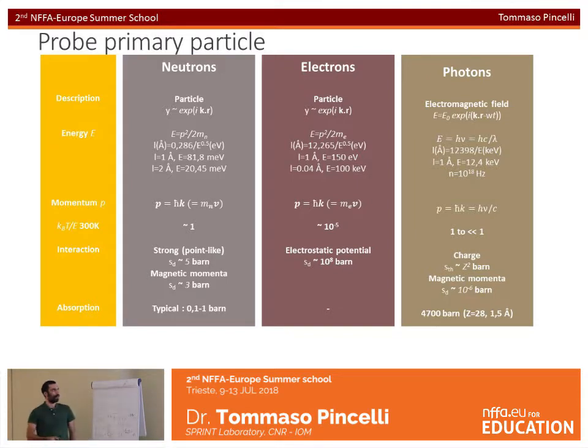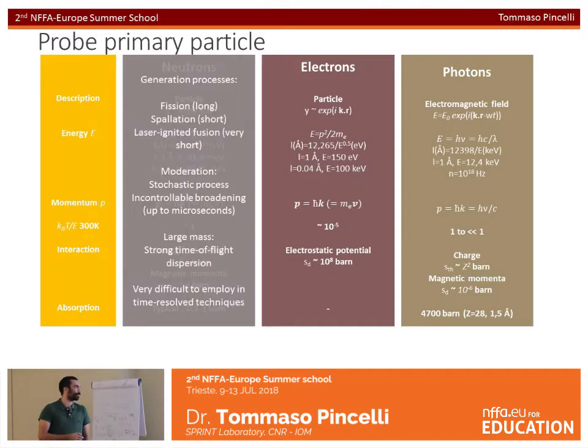The generation processes are fission, spallation, and possibly laser-ignited fusion. Fission is very long and spallation is short, but on timescales of picoseconds. And laser-ignited fusion can be very short, on femtosecond scales, because, once again, it's triggered by a femtosecond laser. But then we have to moderate the neutrons to have the energy that we want. And this is a stochastic process that creates an uncontrollable broadening up to microseconds. So that makes it very difficult to make sharp pulses of low energy neutrons.